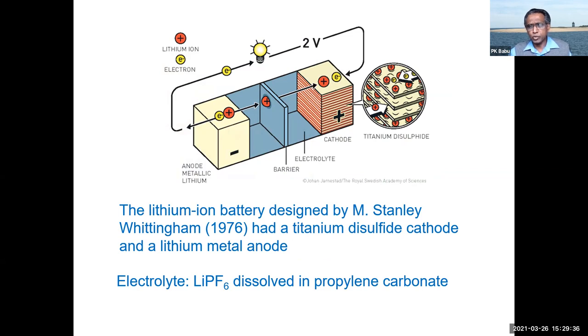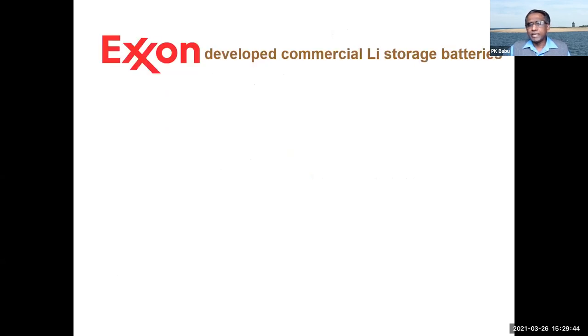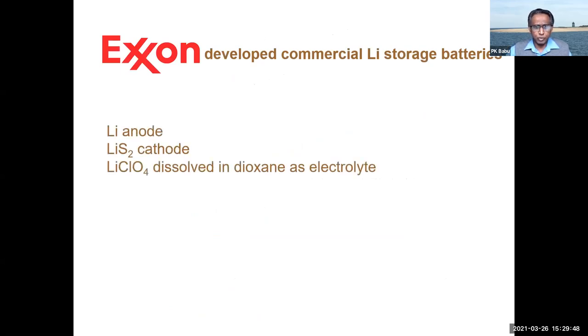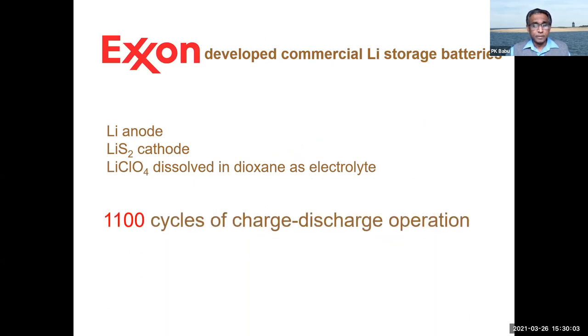With some slight modifications of this, this had an EMF of 2.5 volts. Exxon developed a commercial lithium storage battery, only with very slight modifications. Again, lithium anode, titanium disulfide as cathode, and lithium perchlorate dissolved in dioxane as the electrolyte. The battery could operate for 1,100 cycles of charge discharge.